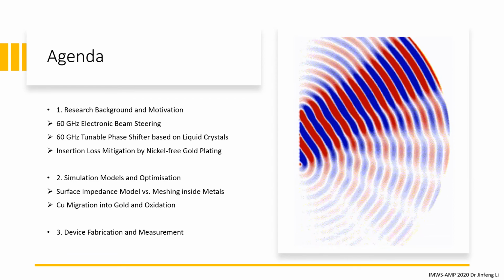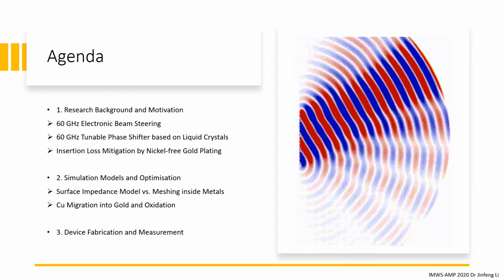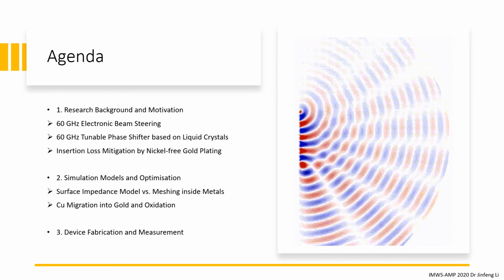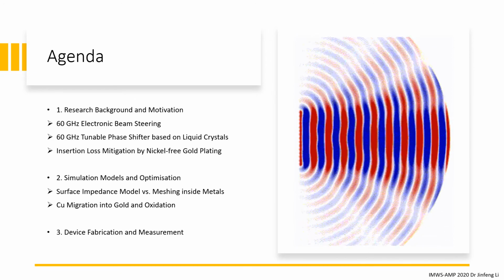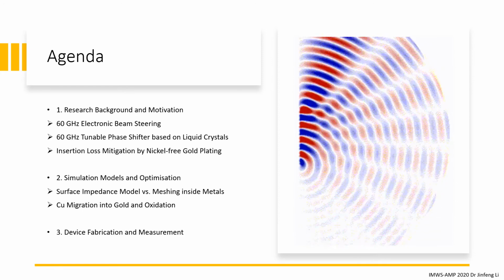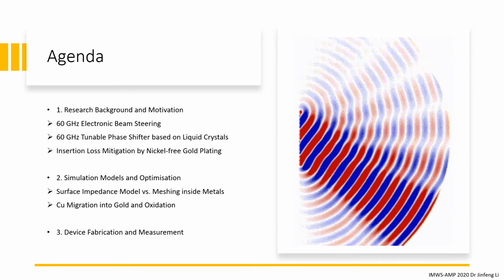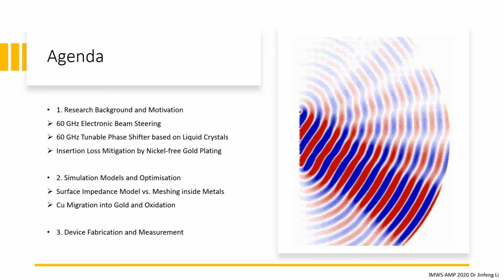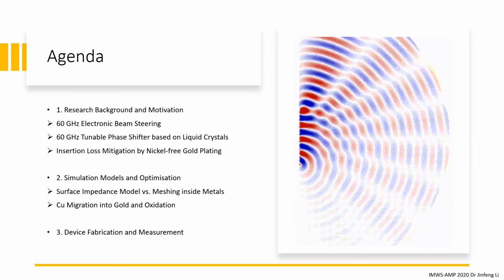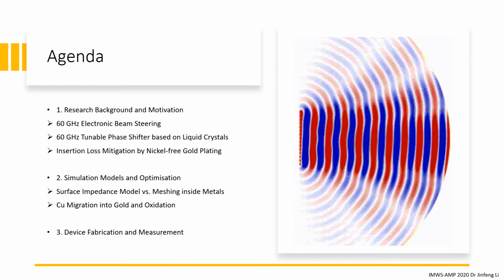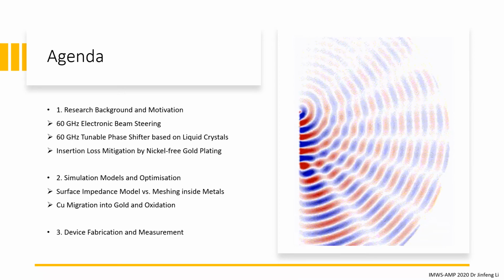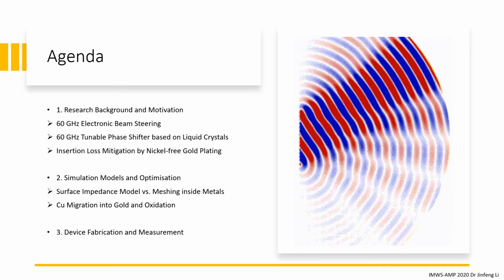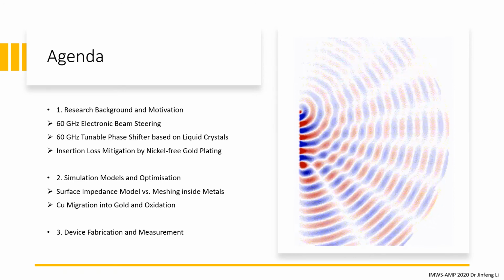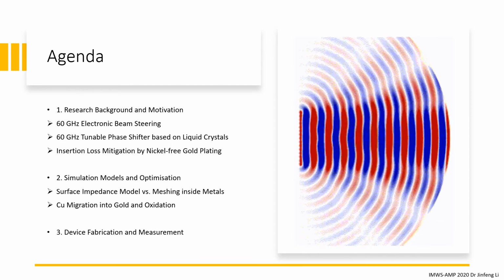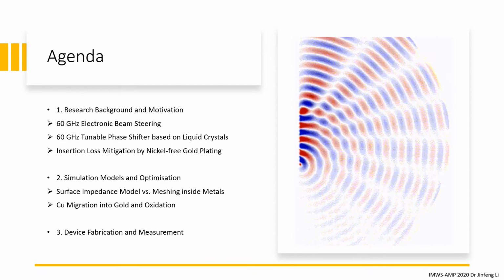In this situation, meshing and solving inside the plated metal can accurately represent the field's decaying behavior without overestimating the conductor loss. In addition, the experimental consideration about the copper migration into gold and oxidation was investigated. Finally, we will show the measurement results of a number of our fabricated devices with different gold plating thickness to verify our findings of the optimum nickel-free gold plating.